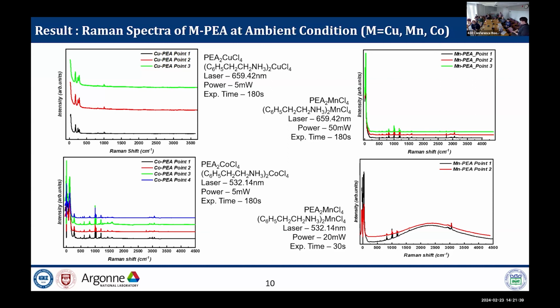Also in PEA2 manganese tetrachloride, we can measure some photoluminescence using the green laser, with a wavelength of 532 nanometers. It means there is some excitation at that wavelength and electron-hole recombination. It can also help to understand the orbital configuration in this material.